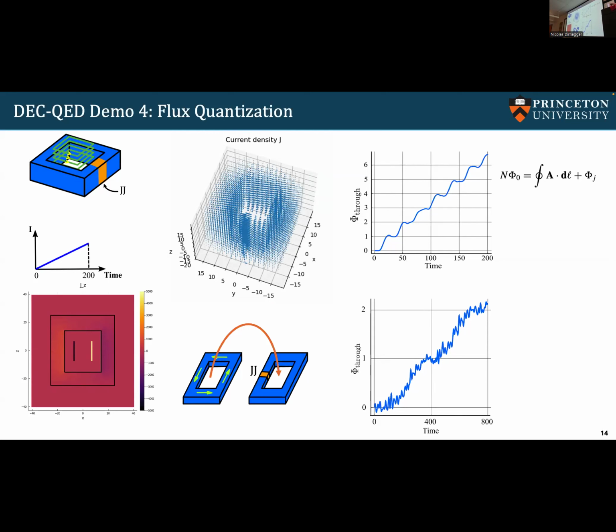current around the junction area. This switching back and forth of the current near the junction area is an indicator of local magnetic vortices being created and transported from the inner boundary to the outer boundary of your junction loop. Every time a vortex is created here due to the penetrating current, because of the Lorentz force it is dragged across the junction.